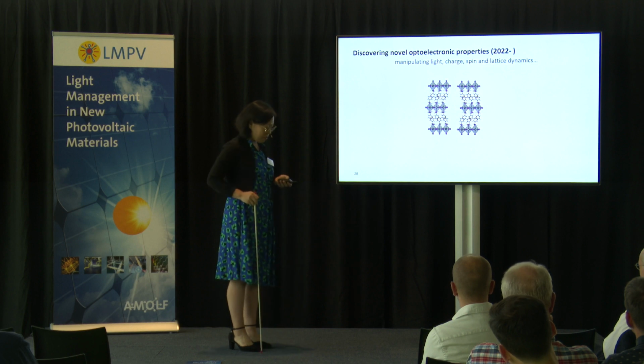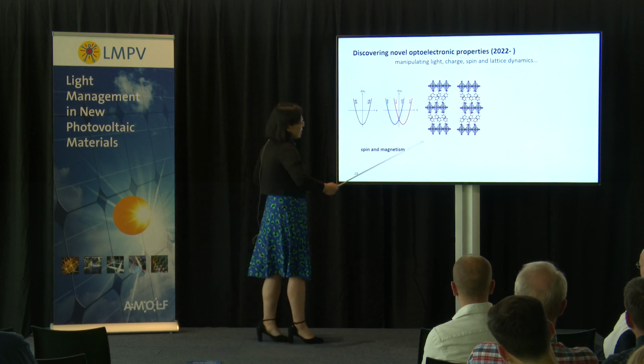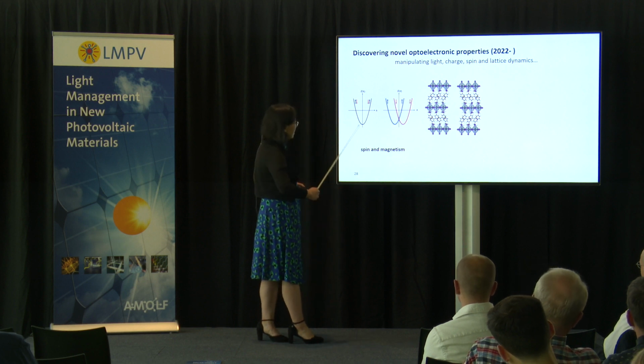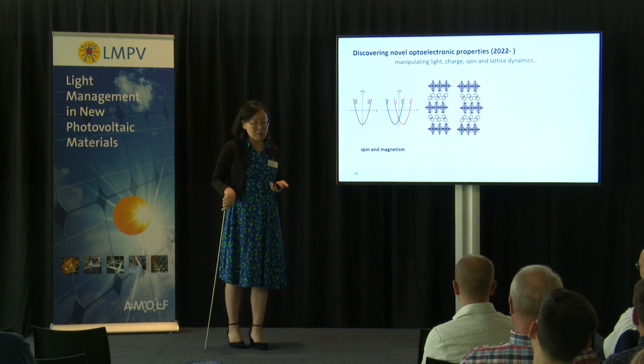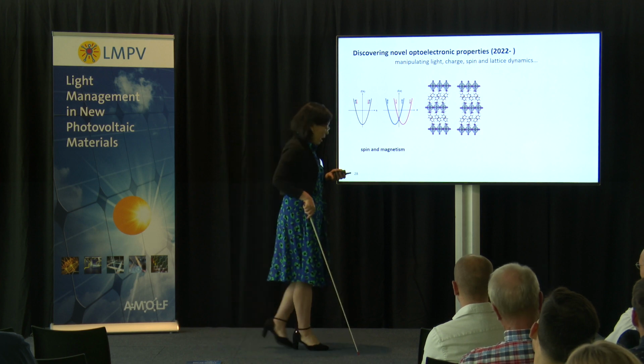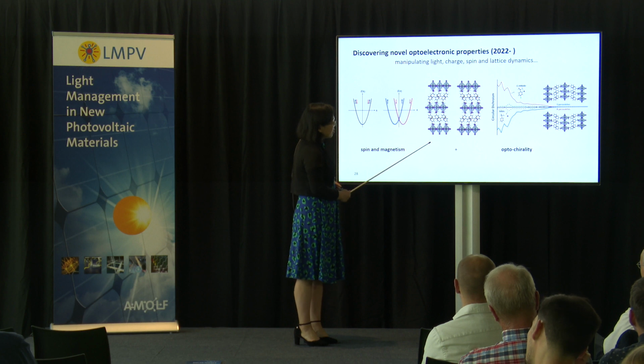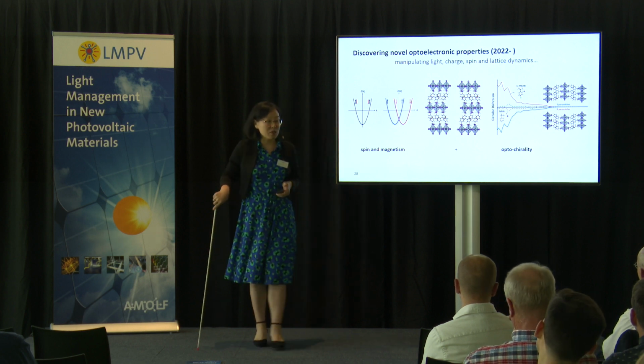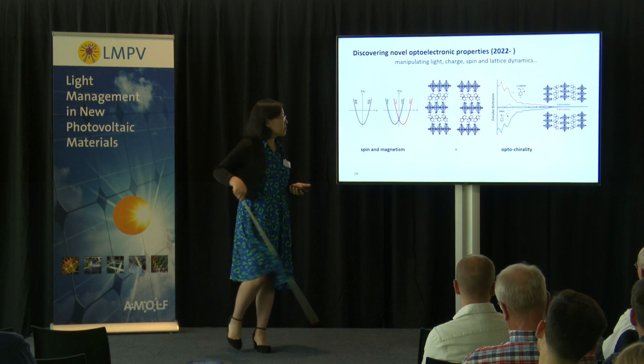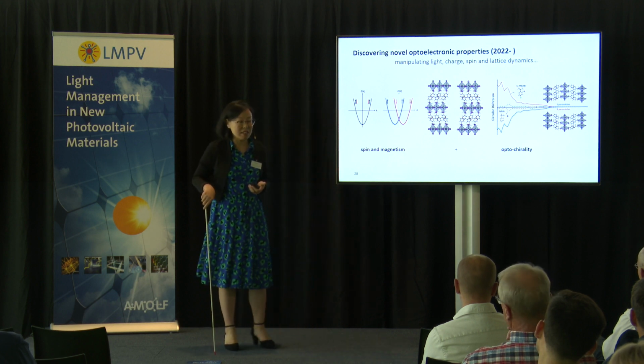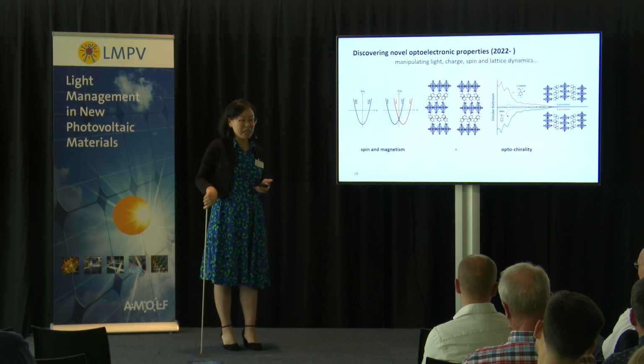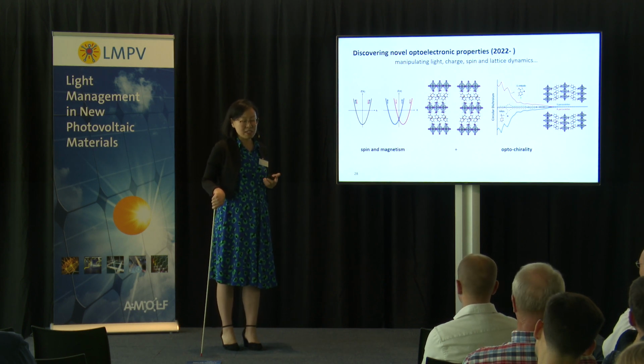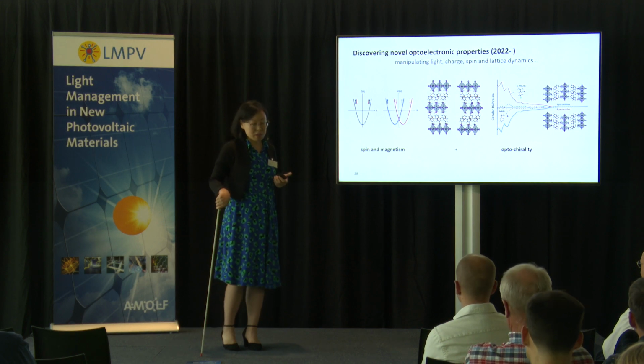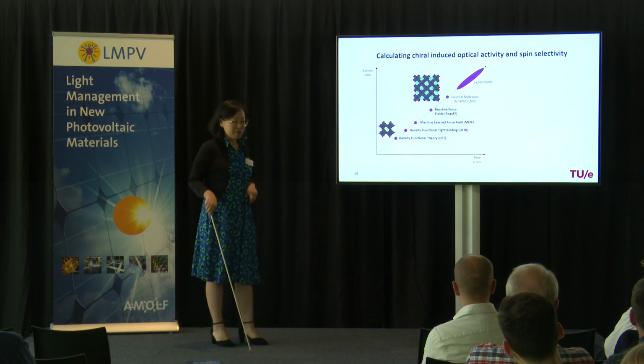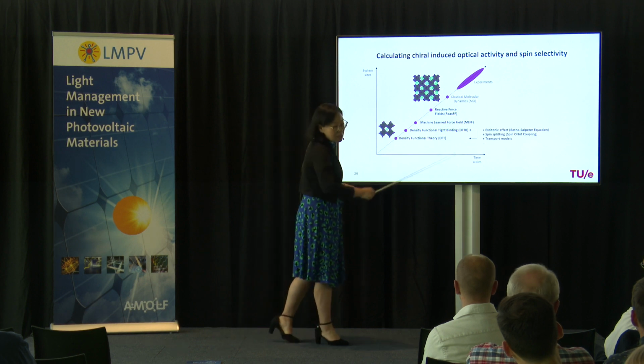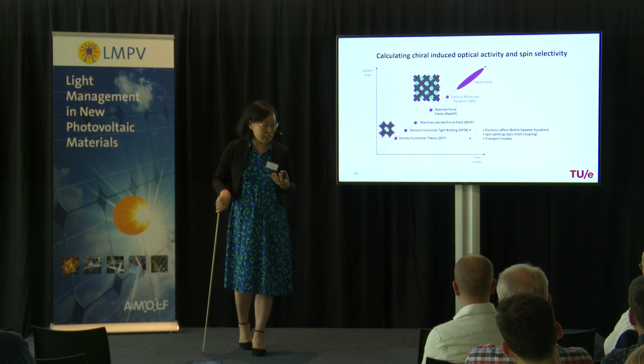And these ligands give very interesting properties because they give induced asymmetry in the lattice. This actually causes band splitting. That means it gives rise to extremely interesting spin magnetic properties. And on the other hand, this chiral molecular geometry also has chiral optoactivity. This allows us to actually detect or absorb left or right-handed light. The combination of these interesting properties gives us many interesting new physics to study in spintronics, in photonics, for information application of quantum materials. And we can use the same set of tools to look at it. But this time the focus is more on the quantum side, because now we're putting all the effort on how charge and light interact.